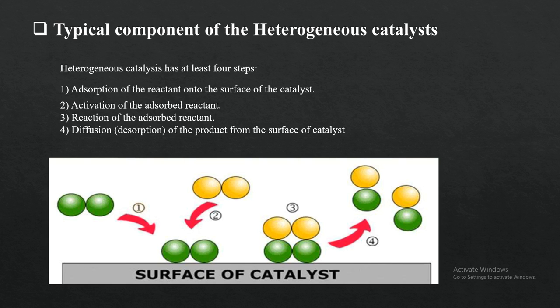It may use the bonding electrons in the molecules and weaken the bond, subsequently making the reactions easier. So in step 2 and step 3, the adsorbate is held on the surface of the metal, in an orientation for the reactions to occur. In step 3, there is a collision between them, and in step 4 there is a rearrangement of the electrons and the product is released.